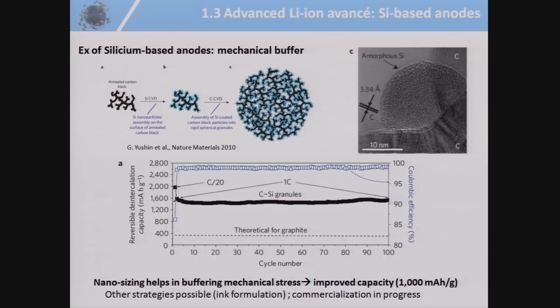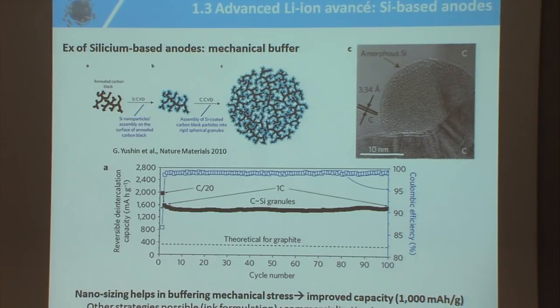How to solve it? This is an example taken from the literature. The idea is to try to use nanostructured silicon anodes. Why? Because if you use nanostructured materials, you can have voids, volume, to buffer the mechanical expansion between the particles.